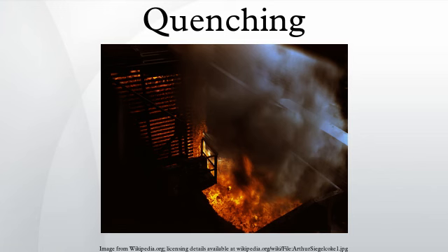Process. Quenching metals is a progression. The first step is heating, that is heating it to the required temperature. Second step is soaking. Soaking can be done by air, or a bath, or in a vacuum. The soaking time in air furnaces should be 1 to 2 minutes for each millimeter of cross-section. For a bath the time can range a little higher.